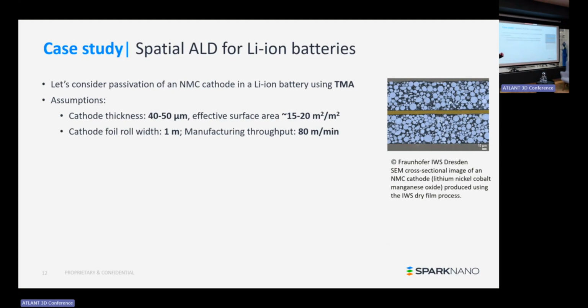Of course, the surface area, because in the end you still need a 40-50 micron, so the surface area doesn't change. So you still need roughly the same amount of precursor because you need to cover the surface area. It's just that the mass flow that you have to supply per stack is lower. Exactly. That can be beneficial. Yeah. It will have consequences in the other manufacturing steps of that.